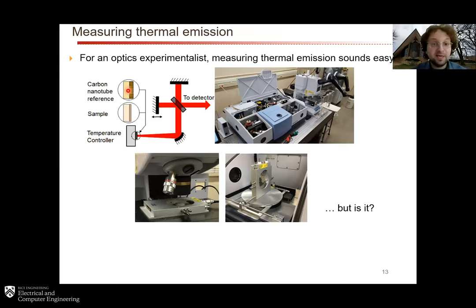Then you take a reference sample, for example, something that's like a blackbody, something very black, like a carbon nanotube forest. You do the same measurement, you compare the two together, you perhaps divide one by the other, and you have, for example, the emissivity. So this sounds like it should be very easy. This is a set of equipment that we collected and then built up in our lab. This is our FTIR, our FTIR microscope, a heat stage that can be placed in various places, including under the microscope and also in the sample compartment of the FTIR, where we can also rotate it to do angle-dependent measurements. So conceptually, this is all very, very straightforward.